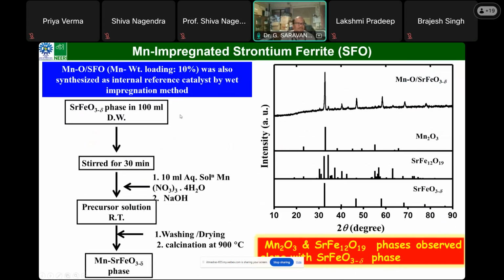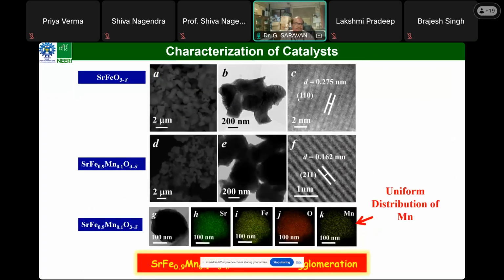So for reference purposes, we need to know whether the lattice substitution of manganese in strontium ferrite influences the catalytic activity or not. So we prepared a reference material with the same combination and the same stoichiometry, but as manganese oxide. Manganese oxide dispersed on strontium ferrite was prepared as a reference material, and again as usual we performed XRD to ensure manganese oxide is on the surface of strontium ferrite and not in the lattice.